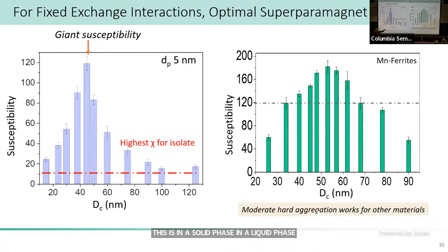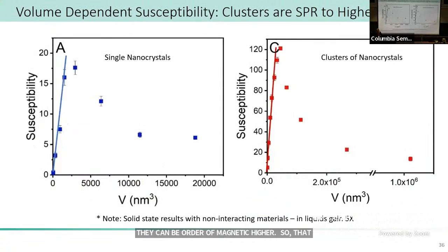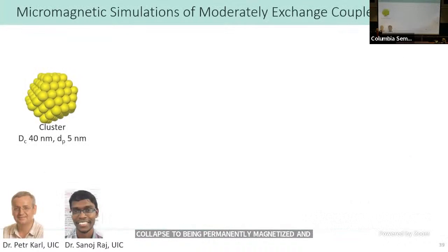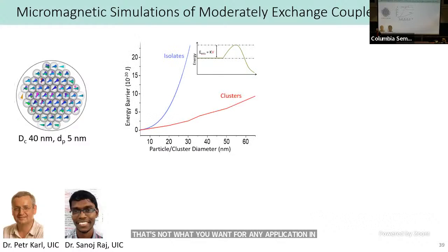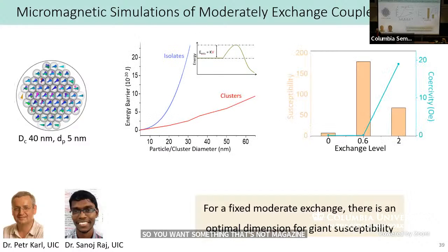So that really high susceptibility, but for very small cluster sizes, is perfect for biomedical engineering applications. This is just another graph showing if you plot versus volume, you can see that there's a strong volume dependence to susceptibility, which we would predict. And if we make them too big, they collapse to being permanently magnetized. That's actually not what you want for any application in the body. So you really want something that's not magnetized at zero field. We have some excellent collaborators who've simulated this, which has been really important for our understanding. The size dependence is fascinating, but I want to talk about how we use them. So let me close with that.